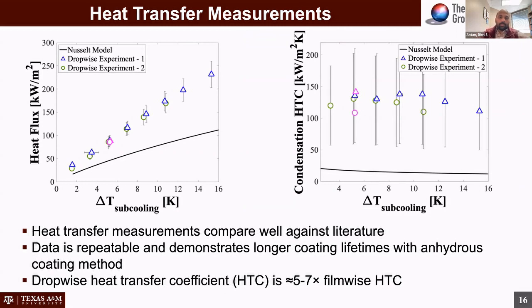You see this again with the heat transfer coefficient measurements. Not too happy with the scale bars. They are rather not scale bars, the uncertainty bars. This method is not the most conducive to getting the high sensitivity to the heat transfer coefficient, and so that's another avenue that we're looking to improve upon. But in general, we see considerably higher heat transfer coefficient enhancements over the film-wise mode.